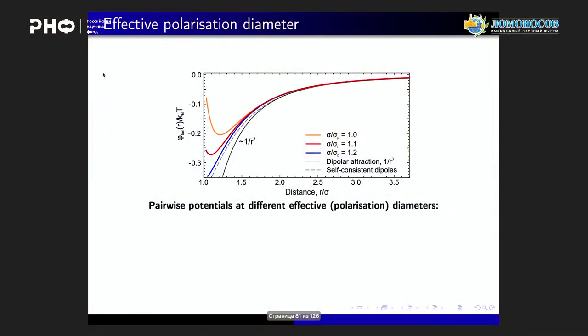And we observed that the attraction in this case is very sensitive to the internal structure of the particles. This is a very prospective result because it means that, in contrast to typical colloidal particles, where interactions are provided by the charged surfaces, with tunable colloids we can design the interactions with the internal structure of particles. And we can even design tunable interactions with an anisotropic distribution of the potential.